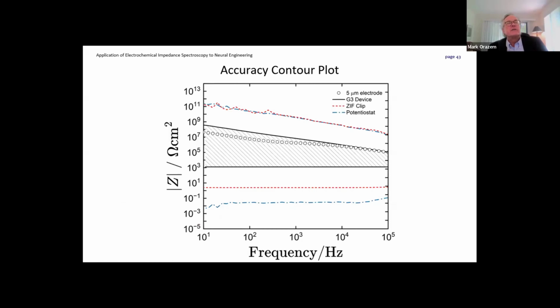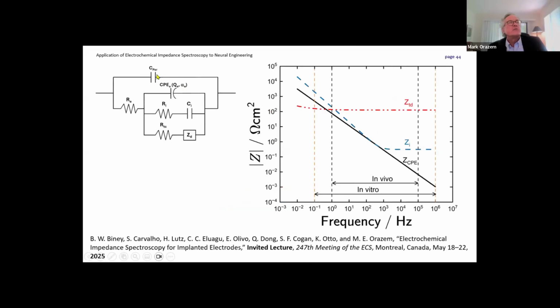And this is showing you some of the data we collected for a 5 micron diameter electrode. What we're seeing is that at high frequency, we are effectively measuring the impedance of the wires. So that means that when we build a model for this, we have to take the capacitance of the wires into account. And that's what we're doing over here. This is the capacitance of the wires, and that is going to be in parallel to everything that we care about. Here is the ohmic resistance.